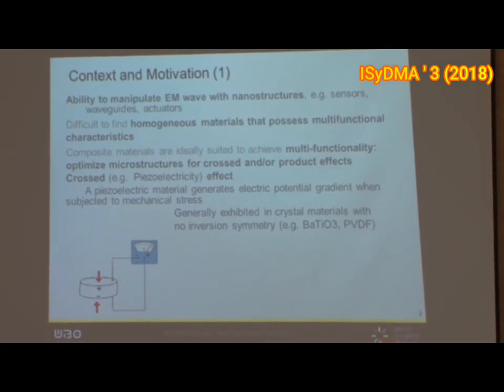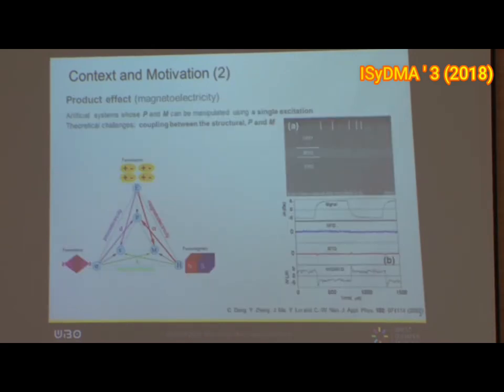Another interesting product we're working on is the product effect, like typically magnetoelectricity. There are two ways to realize this: the direct coupling between the two order parameters of the system, polarization on one hand and magnetization on the other. You can directly realize the coupling, but experience tells us it's very difficult to realize in practice, and the magnetoelectric effect is very weak and requires very low temperature.